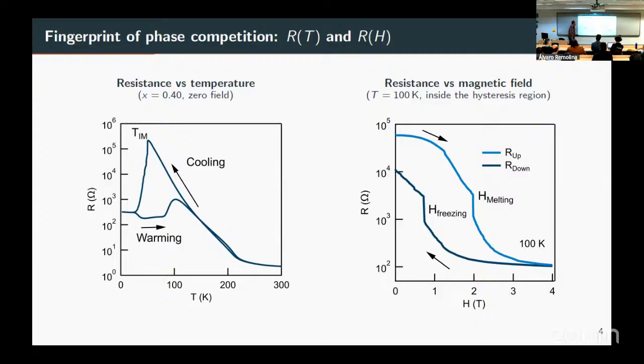And then you go up in temperature, you have this funny looking hysteresis, this region here, which is a plateau. And then you have this hysteretic region, which is interesting. The physics here is that by having this metal insulator transition, we are inducing ferromagnetic domains into the sample. Those domains percolate, and the percolation threshold happens exactly at this point. So you have a network of ferromagnetic domains that connects, and that's why the resistance goes down so abruptly. Okay, then we have the magnetoresistance effect.